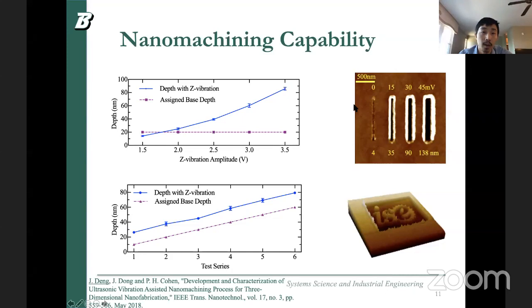Besides the XY, we also have control of the Z vibration. If we increase the Z vibration amplitude from a certain point to a larger value, we can see the actual depth. This is the actual depth, and this is the design depth. For all the experiments, we designed 20 nanometer depths, and with 1.5 volts of Z vibration, it is a little bit smaller than 20. While we increase the vibration amplitude in the Z direction, the depth actually increases.